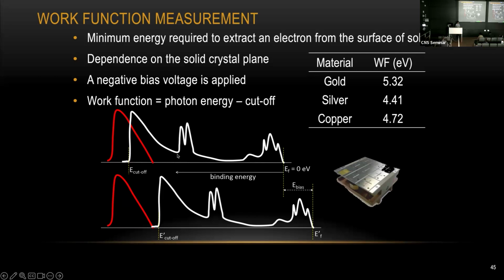So for instance, if you bias your sample by 10 volts, you can shift your entire spectrum to the left by almost 10 eV. By showing this edge here, we can determine your Fermi level and your cutoff energy. Then we can do some simple calculation. The work function is simply your photon energy minus your cutoff energy. So for instance, pure gold should have a work function around 5.3 eV, silver a little bit lower, and copper is about 4.7 eV. So that's how you can do some work function measurement using XPS.